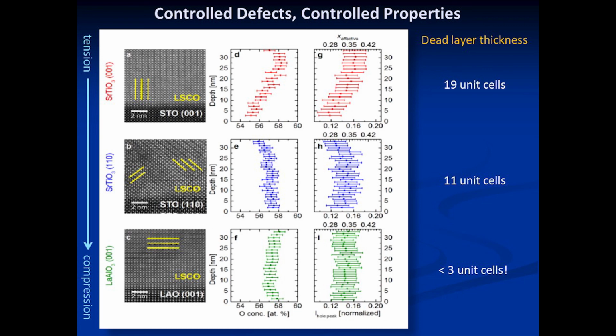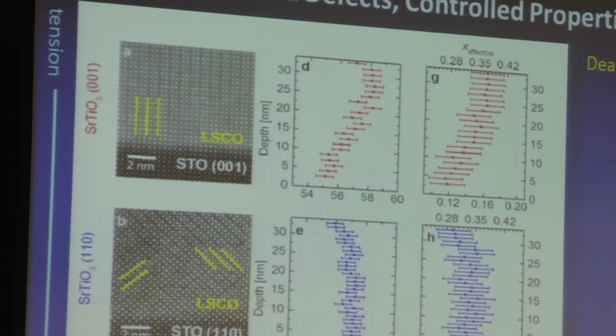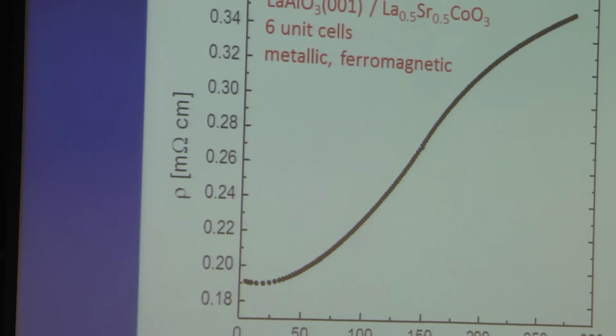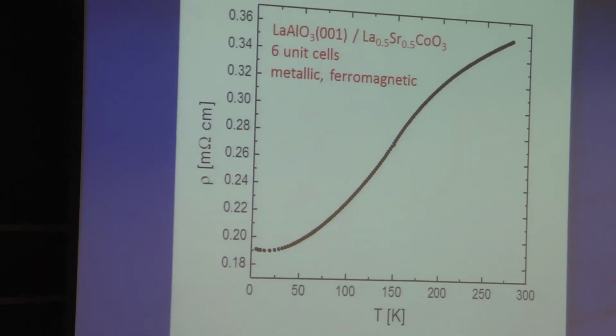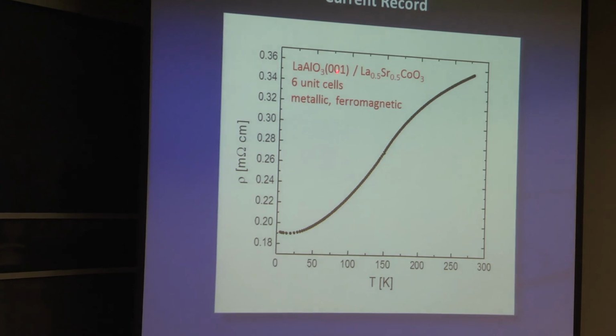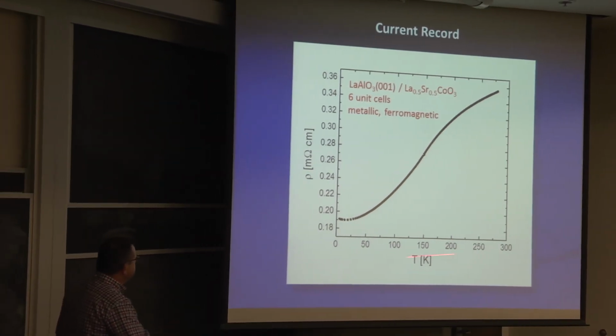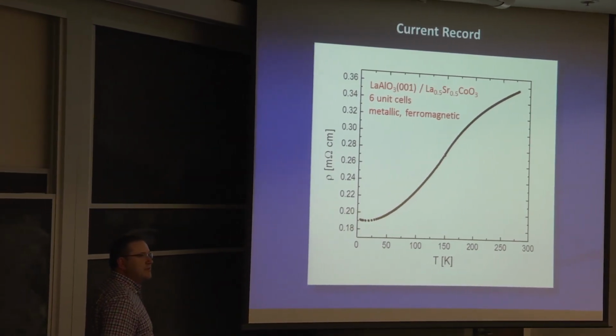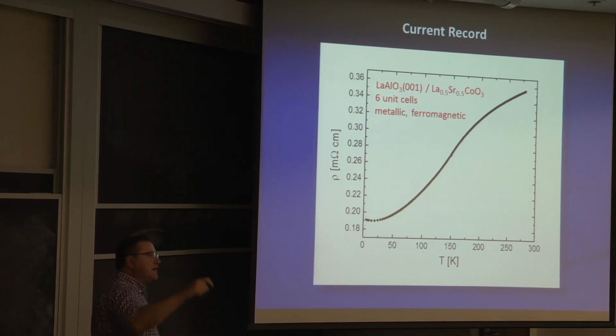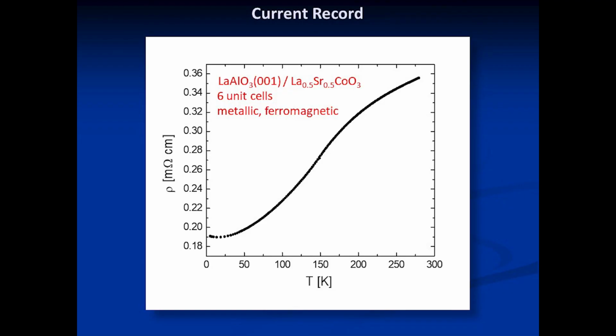I'll show you our guess. Best is it's less than 3 or 3.5 unit cells if you properly choose the substrate so you can manage these oxygen vacancies. So this is the kind of thing that is as good as we can do. It's about 6-7 unit cells thick. It's a metal, resistivity versus temperature just looks like it is in the bulk. And if the dead layer at the top is the same as the dead layer at the bottom, then 6 divided by 2, about 3 unit cells, is the thickest that dead layer can be. We've come a long way since growing them on the 001 surface where it was 20, and some people were getting even bigger numbers, right?